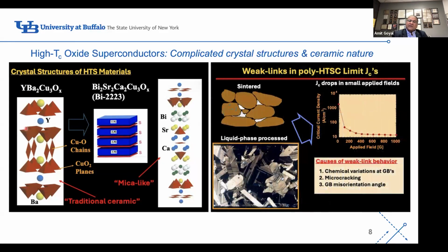So the 90 Kelvin superconductor looks like, in fact, all of these superconductors look like mud in your flower bed. You can use the most advanced ceramic processing techniques to create beautiful microstructures like this one over here, where you're looking at twin planes along the 110 direction within a grain. Even when you have these beautiful microstructures starting from this mud-like material, when you pass a supercurrent through a material divided by the cross-section area, you only get about 1,000 amps per centimeter squared. And when you apply a magnetic field, where most applications are in high magnetic fields, the current carrying ability drops dramatically. And this happens because of issues at grain boundaries and micro cracks. This is, after all, a traditional ceramic material.